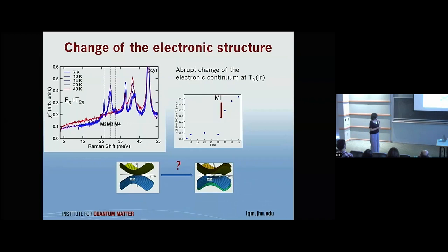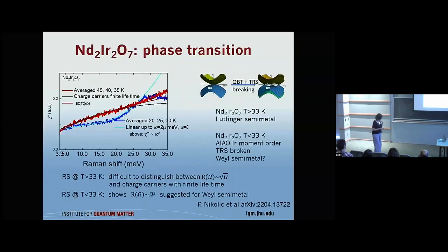And so then we looked at this and we fit it with basically functions for this electronic continuum. We wanted to be very, very honest, and we checked if the continuum at higher frequencies, higher temperatures, could be explained by charge carriers, just quasi-free charge carriers. This is something which is known well. It is actually very close to what we'd get from quadratic band touching, but then the parameters which we'd get would mean very, very large scattering for the quasi-particles. Metallic quasi-particles would not be in agreement with anything else which is known about these pyrochlores. So like a couple of orders of magnitude higher.